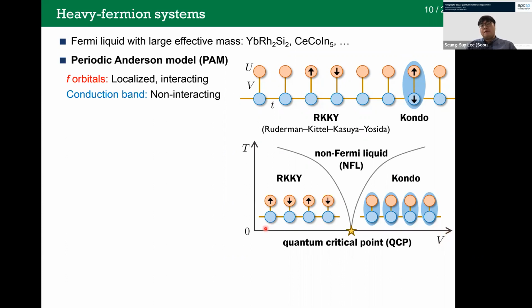In the other limit, when V is small, then the Kondo screening is suppressed exponentially because the Kondo temperature depends on this hybridization in an exponential way. So the RKKY interaction wins. So we call this phase the RKKY phase. And between these two phases at zero temperature, there is a quantum phase transition at the quantum critical point. And this point becomes a finite region at finite temperatures, forming this kind of quantum critical fan. And the physics here is governed by non-Fermi liquid behavior.